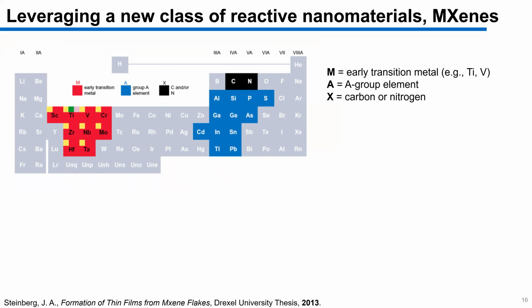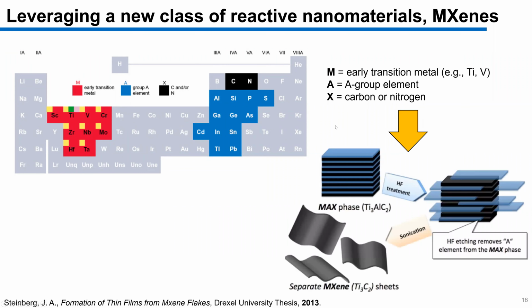PFAS in water. And what we have been focusing on is the potential use of these reactive nanomaterials called MXenes. They are derived from what are called MAX phase metal composite materials. The M in MAX stands for early transition metals, as shown in the red here in the periodic table. It's sandwiched by an A group element, for example aluminum, shown in blue here. And then the bottom layer is X, which is either carbon or nitrogen. If you apply hydrofluoric acid to selectively etch the aluminum layer, then what you are left with is called MXene. So, taking away that A layer, you're left with an MX composite material.